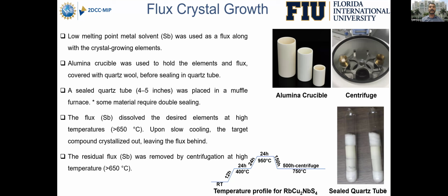But the difference here is that we increase the temperature of this furnace higher than the melting point of the material, and the operating temperature needs to be higher than the melting point of the flux. In this case, the melting point of antimony is 650 degrees C. So you can see from the temperature profile, we ramp up the quartz to 950, which is higher than 650, the melting point of antimony, and slowly cool it down to 750. So 750 is still higher than the melting point of antimony.